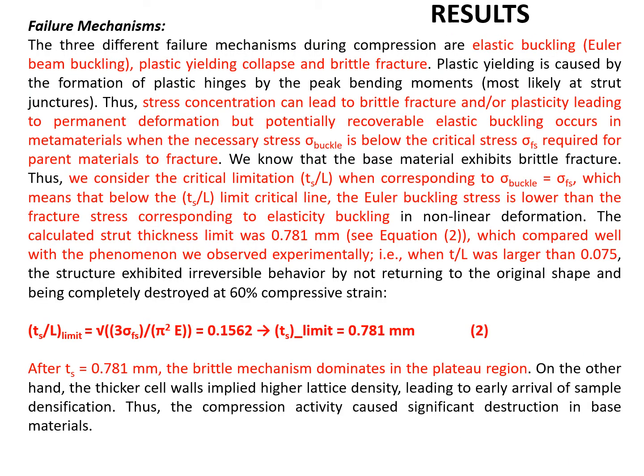As far as the failure mechanisms are concerned, we can consider 3 different failure mechanisms during compression. We have elastic buckling based on Euler's theory, plastic yielding collapse, and brittle fracture. The stress concentration can lead to brittle fracture or plasticity leading to permanent deformation, but potentially a recoverable elastic buckling occurs in metamaterials when the necessary stress is below the critical stress sigma_Fs required for the parent material to fracture.